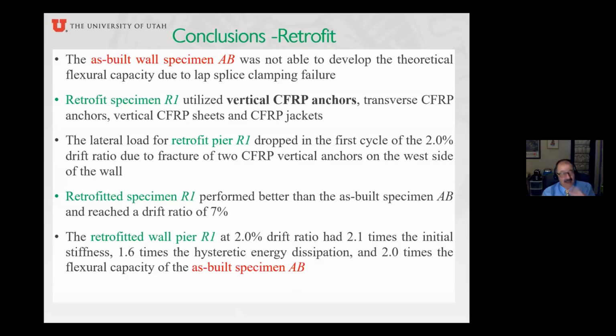And I'll summarize the conclusions, because there are 6 tests here, and there is retrofit and then there is repair. I summarize in 2 groups. Let's talk first about the retrofit. The as-built wall specimen was not able to develop the theoretical capacity because the lap splice failed. The first retrofit, with the vertical anchors and transverse anchors and vertical sheets and hoop carbon fiber sheets, that was the first retrofit, R1.